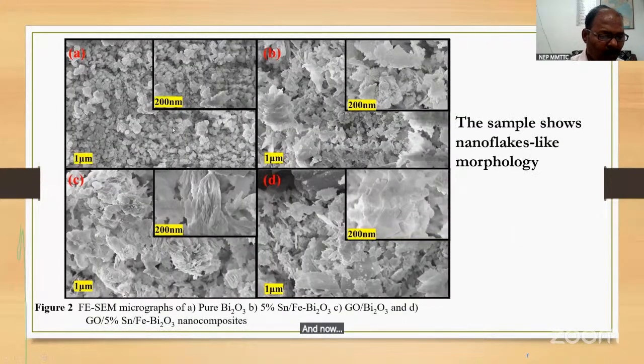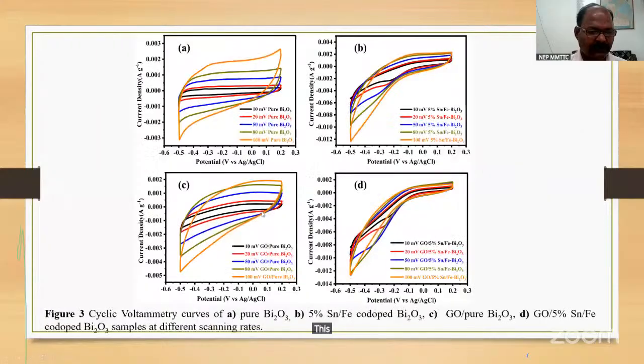And now, here these are the field emission scanning electron micrographs. Here is agglomeration, but here are some sheets. You see here, sheets are formed. Okay, nanoflake-like morphology this sample shows. And now this is the CV curves of pure and 5% tin iron co-doped bismuth oxide. Okay.